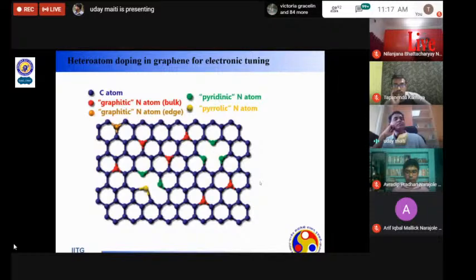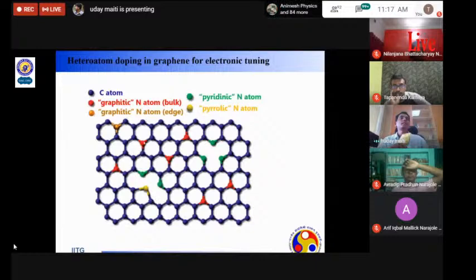So graphene is made up of carbons, but if you replace carbon with some other heteroatoms like nitrogen, sulfur, phosphorus, you can change the electronic property locally. And depending on their dopant site, where the individual dopant atoms are, they have a different arrangement. You can see that here my atom is connected with 2 carbon atoms only. But if it is here, it is connected with 3 carbon atoms. This is known as the graphitic nitrogen, whereas here this is known as the pyridinic nitrogen.